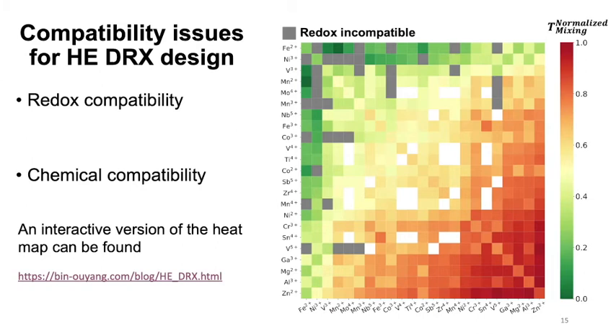For example, when manganese 3+ is in the same structure with vanadium 3+, because of their difference in equilibrium potential, charge transfer will happen between manganese 3+ and vanadium 3+, oxidizing vanadium 3+ to vanadium 5+ while reducing manganese 3+ to manganese 2+. And this tells us that manganese 3+ and vanadium 3+ are not redox compatible, so they should not be put in the same composition when you design the high entropy DRX materials.